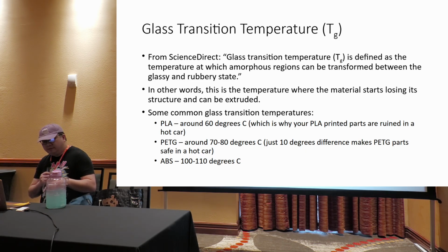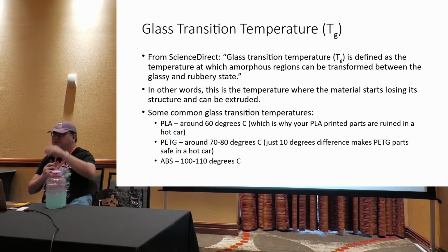Some common temperatures that this happens: PLA is 60 degrees Celsius. This is why you cannot have a PLA printed part in a hot car, because a hot car can easily get up to 140, 150 degrees Fahrenheit, which is around 60 degrees Celsius. And remember, this is a spectrum. It's not that you hit 60 degrees and your PLA parts fall apart. It's over a range. So putting it in a hot car at 80 degrees will probably also ruin the parts. So this particular property is why PLA does not work in a hot car.